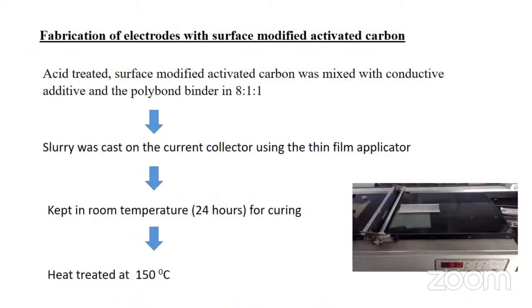The fabrication of the electrode with surface modified activated carbon. Acid treated surface modified activated carbon was mixed with conductive additive and polybond binder in 8:1:1 ratio. The slurry was cast on the current collector using the thin film applicator. You can see in this picture the thin film applicator. The electrode was kept at room temperature for 24 hours for curing. After that, it was heat treated at 150 Celsius.